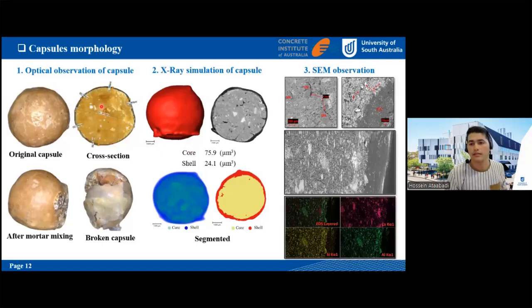Here you can see some morphology of the capsules. You can see the capsule produced is in a very spherical shape, and you can see a very thin layer of the shell material all around the core material that covers the whole surface.